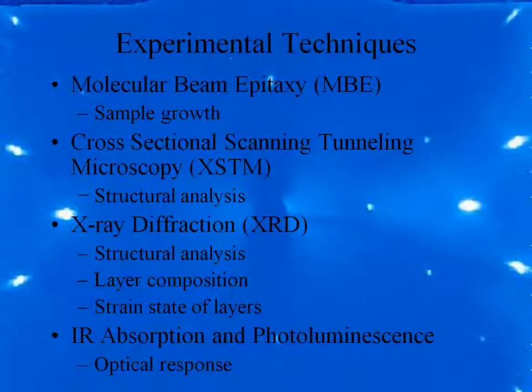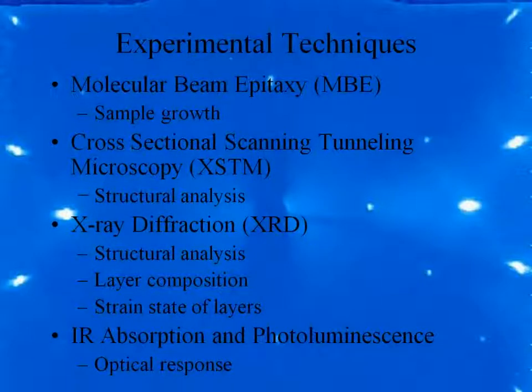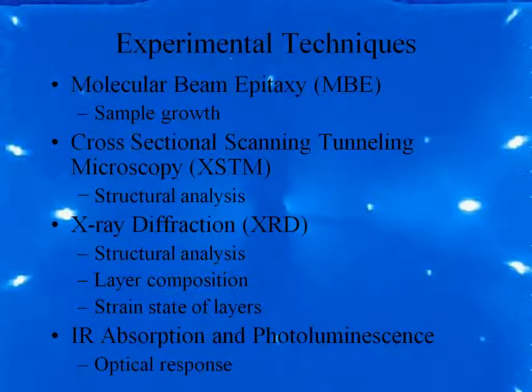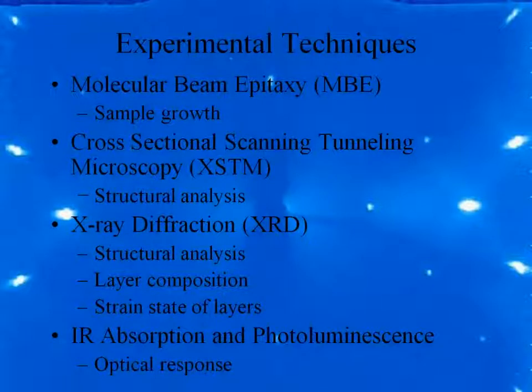The experimental techniques used for this project: samples were grown by molecular beam epitaxy and then structurally characterized by cross-sectional STM, x-ray diffraction, infrared absorption, and photoluminescence. By studying the optical response of the device we can see if the LCM has affected properties in a good or bad way. We also want to determine why the lateral composition modulation occurs by studying the structure to understand what happened during growth.